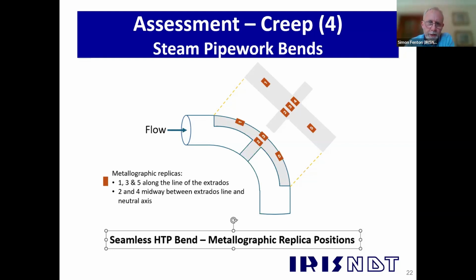Now this slide is applicable to a seamless bend. Now we do have in the UK examples of bends that have been seam welded. There could be multiple seam welds, one on the intrados, one on the extrados, for example. And that gives us a requirement to throw more replicas at the inspection. So we could be looking at up to 15 to 20 replicas per bend. So it's a lot of effort to monitor for creep damage. Next slide, please.